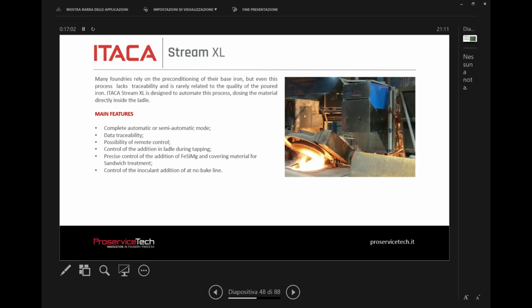You can also make an automatic solution. For example, you want a level of preconditioning that is 0.2% at the beginning of the melting furnace, and the longer the time, the higher the amount can be. So if you have an oxidation factor of the furnace, you can automatically increase from 0.2 to 0.3, from 0.2 to 0.4, ladle by ladle when you empty the furnace. Or, for example, when you hold the iron too much, you can automatize the increasing of preconditioner in the ladle completely